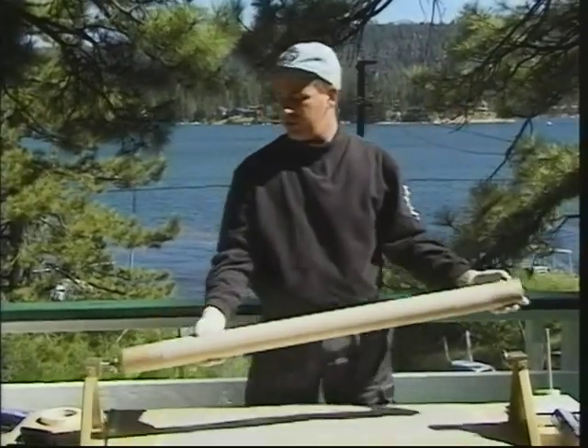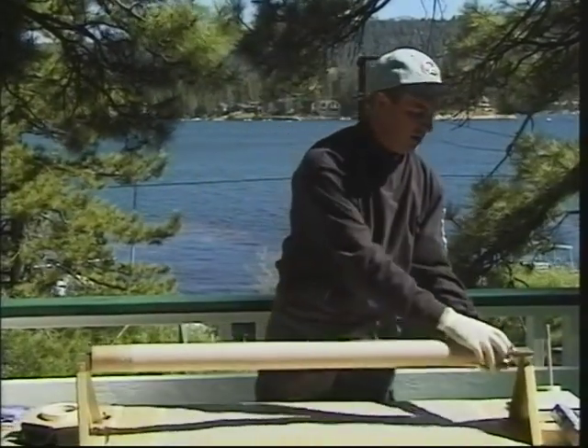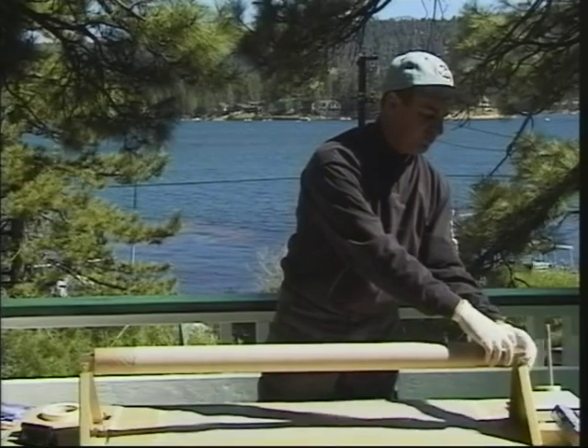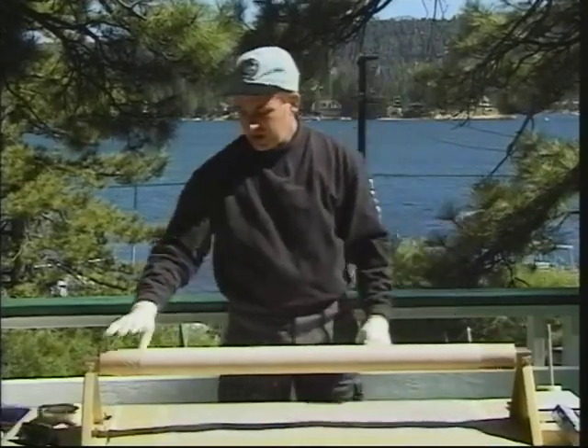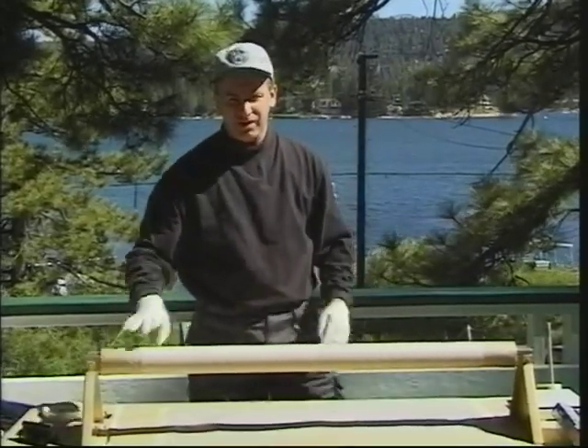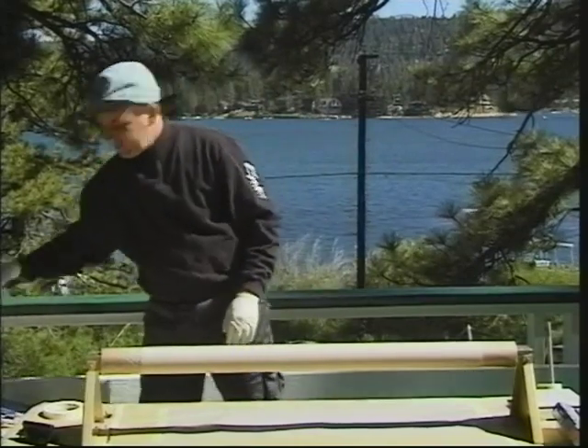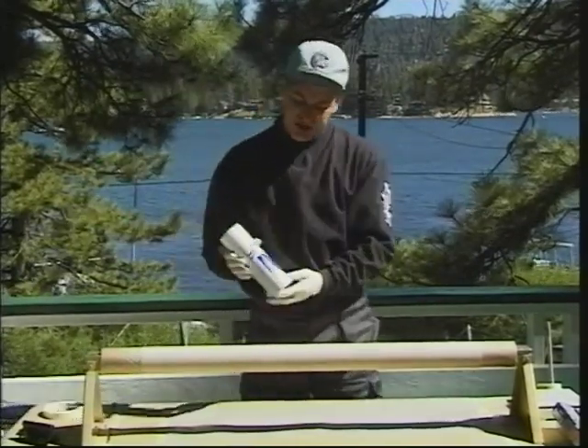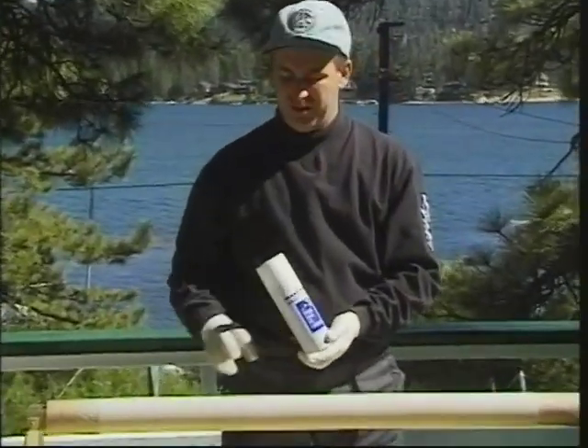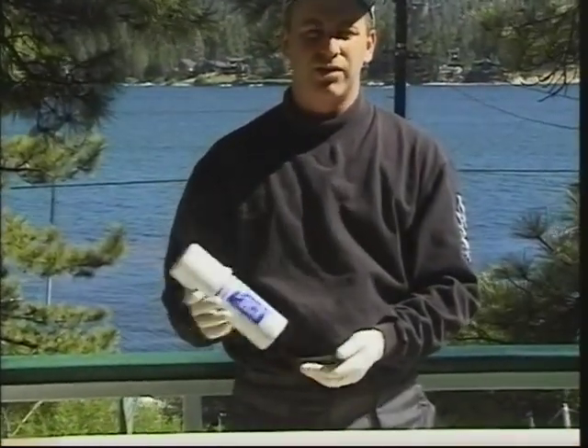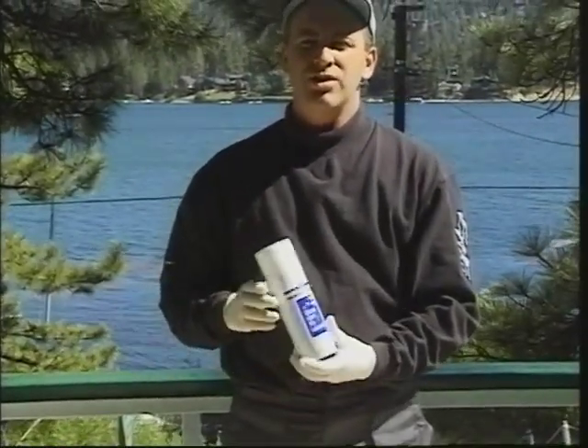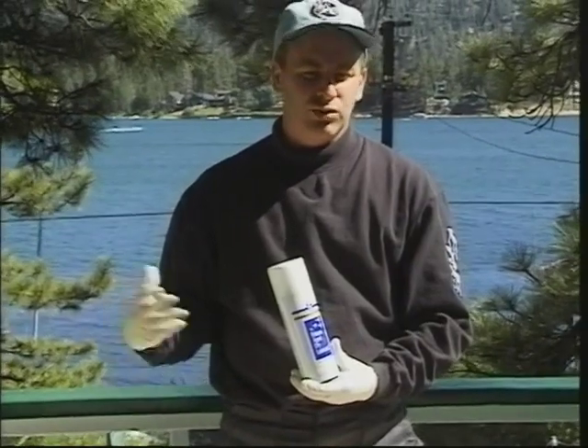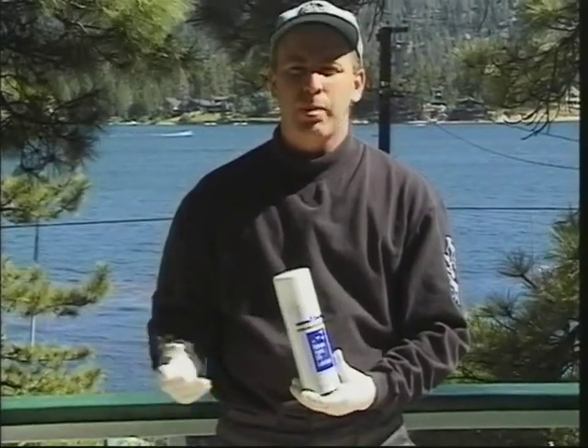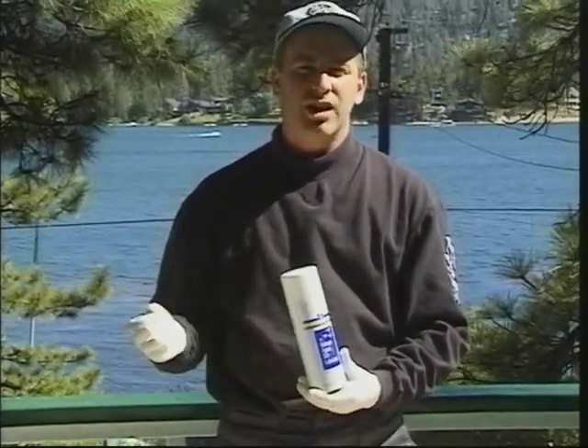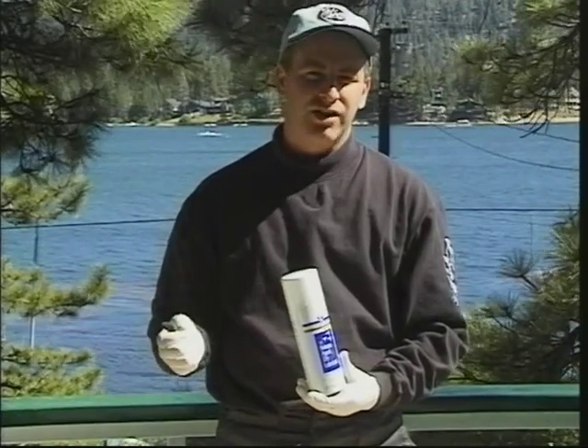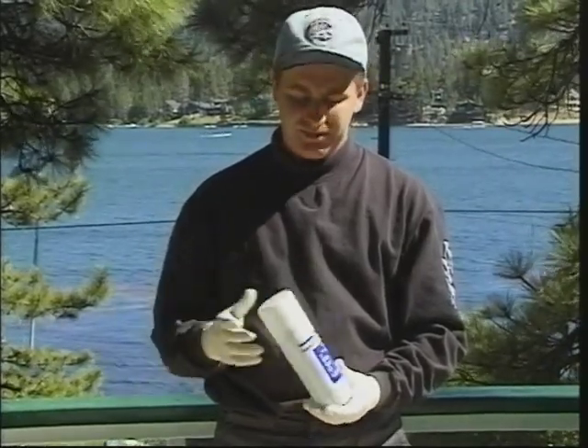I've got another tube prepped, ready to go. This tube is prepared the same as the other tubes, except I've used a release agent on the tube. I sprayed this onto the tube. This is a dry release agent. You can use any kinds of dry release agents like carnauba wax, but use one specifically called out by your vendor catalogs as used for epoxy release.